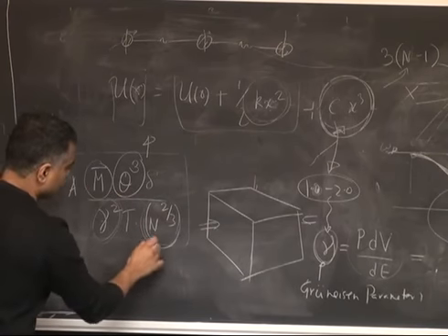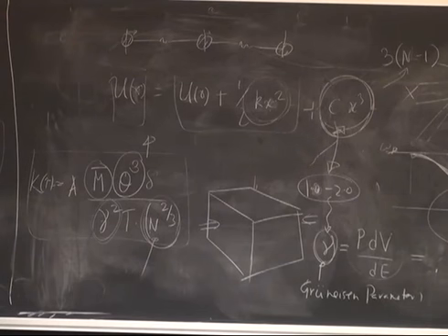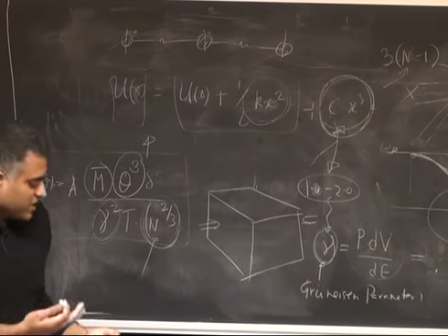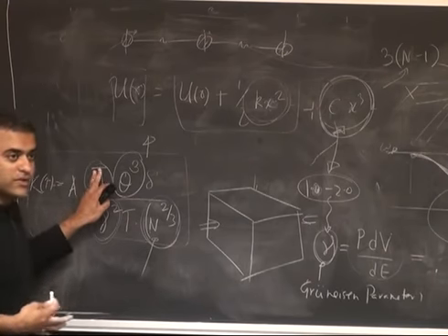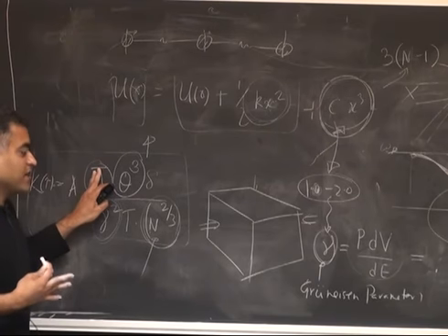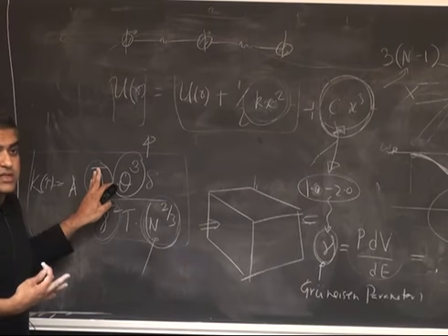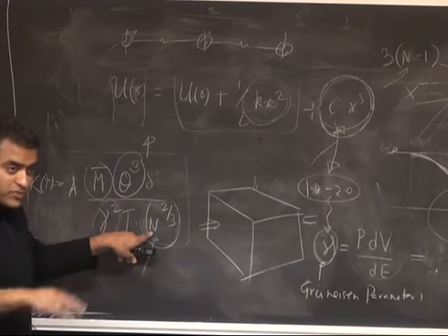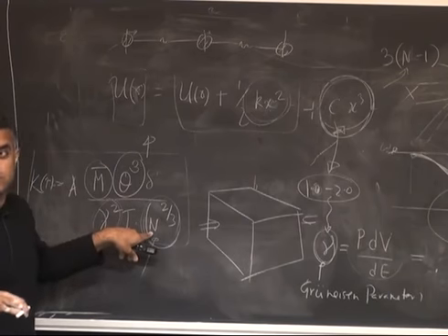But then also you need very simple crystals, where the number of atoms in the basis is not very high. So for high thermal conductivity, the three requirements are high Debye temperature, small Grüneisen parameter, and small number of atoms in the basis. Diamond really satisfies this in a beautiful way, which is why you get a very high thermal conductivity. The point here is light atoms are not enough. You look at gallium oxide or aluminum oxide, sapphire, their atoms are very light, aluminum and oxygen, but the thermal conductivity is abysmal. The reason is the Grüneisen parameter is not right, meaning it's high, and there are 5 atoms, Al2O3 or Ga2O3.